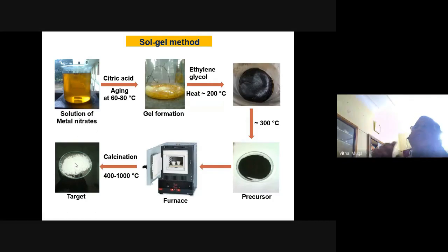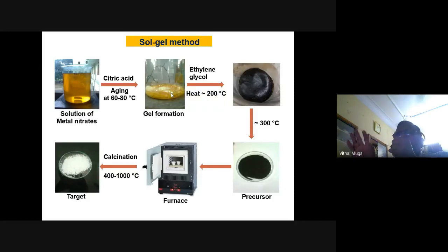Now this gives nano-sized as well as bulk material also. So essentially what happens when you put in ethylene glycol, it polymerizes, and inorganic ions are trapped in the organic matrix, and when you decompose it, the organic component, whenever it decomposes, liberates energy, because 99.9999% of organic reactions are exothermic reactions. So it liberates heat. That heat liberated is picked up by the inorganic ions, and bulk material that you prepare at 1000 degrees, you can prepare at only 400 to 500. In fact, one of my students has done something slightly different. Instead of the sol-gel method, they have used an inorganic metathesis method to prepare nanomaterials at as low as 500 degrees centigrade for materials such as barium titanate, etc.